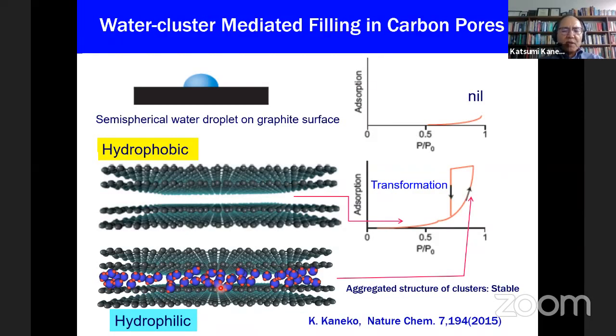They gain very great intermolecular interaction stability and also weak interaction with the wall, and they form an almost complete hydrogen bonding state. So the cluster loses the electrostatic nature. Then they behave like neutral molecules. They are just suddenly adsorbed in very small pores.